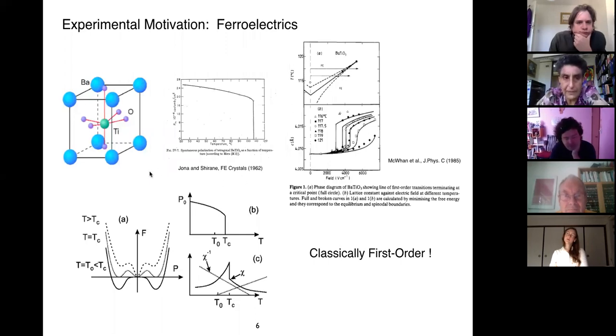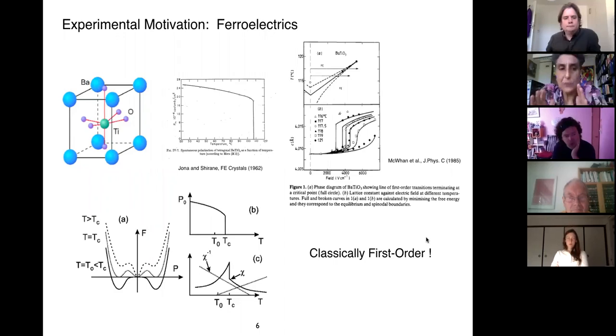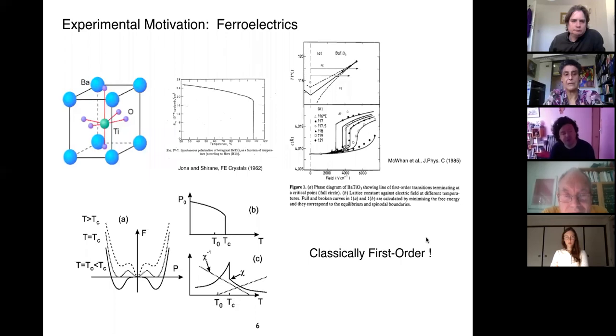So the crucial thing here is that barium titanate is a classical first-order transition. Now, Dennis McWhan also did some nice measurements where he showed that if you clamp the system, that is, if you don't allow any volume change, then actually the transition is second order. You have a diverging specific heat. However, if you unclamp the system, it becomes first order. And he used that to suggest that it's the coupling to the phonon that is crucial. So electromechanical coupling is crucial in making this first order.